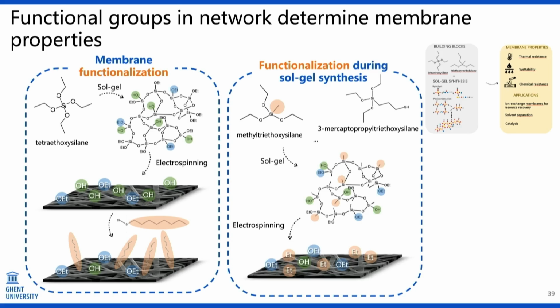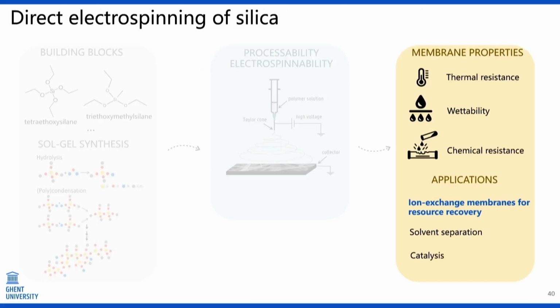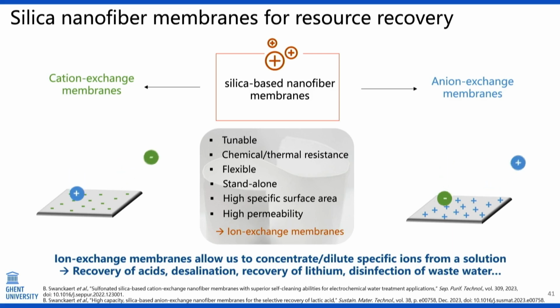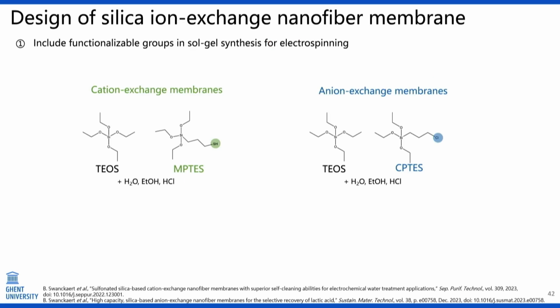Or you can immediately use a more hydrophobic precursor or a functionalized precursor during synthesis. And these can then be used for applications such as ion exchange membranes, solvent separation, and catalysis. So for ion exchange membranes, we developed them for both cation and anion exchange membranes for resource recovery. And the strategy was similar. We did a sol-gel synthesis of TEOS combined with another precursor, which was loaded with a functional group.